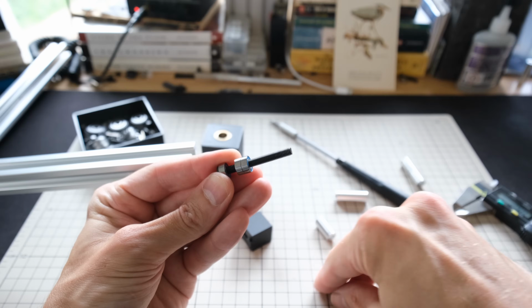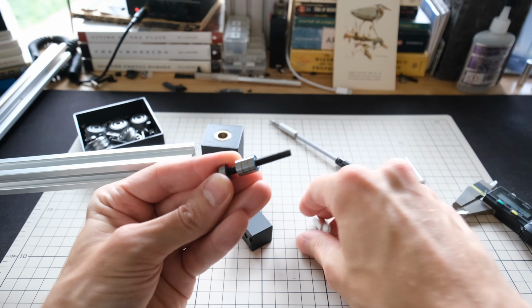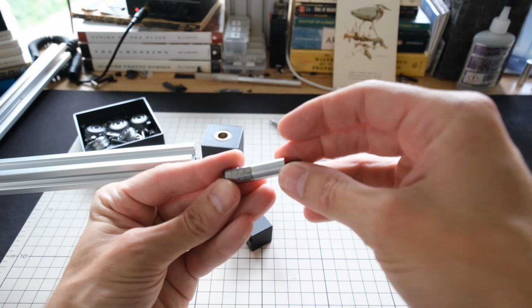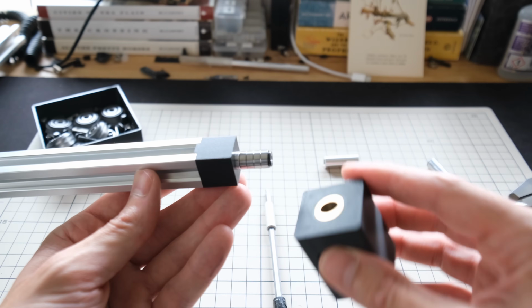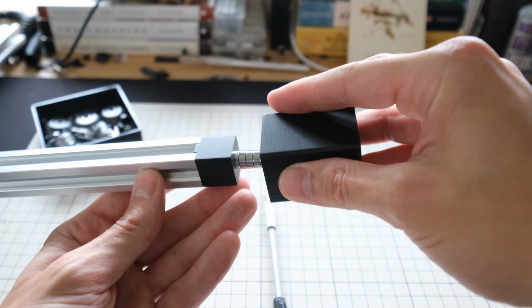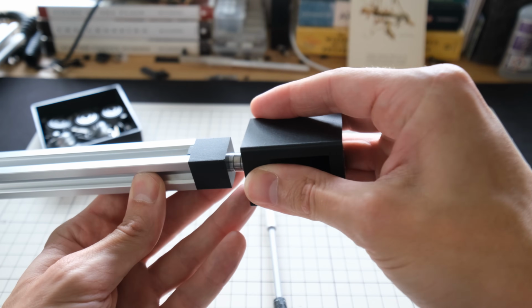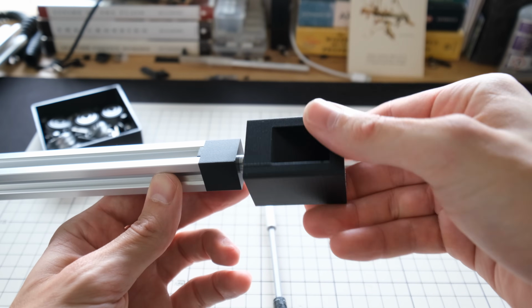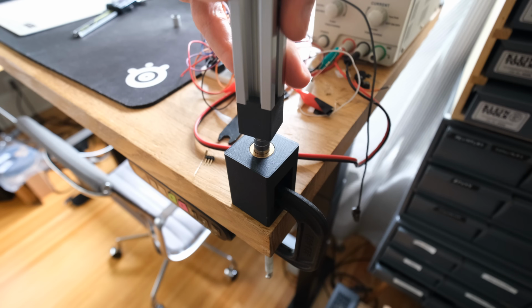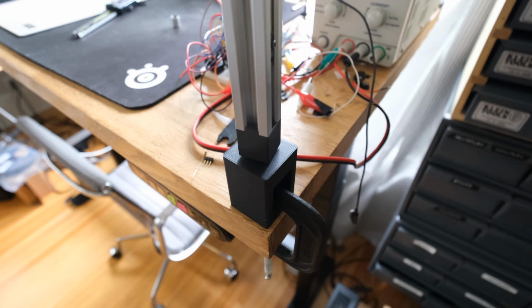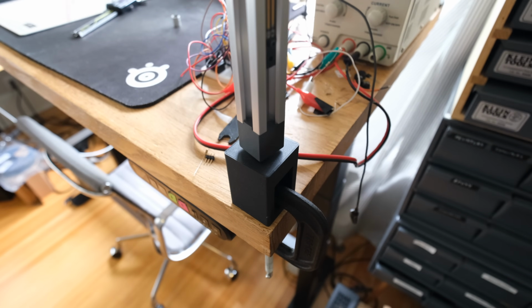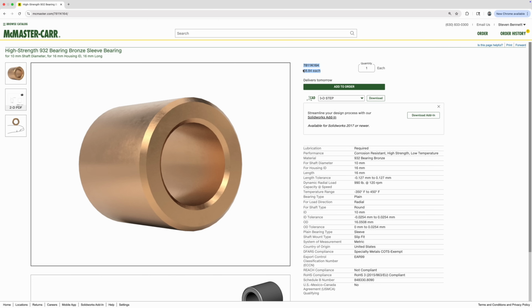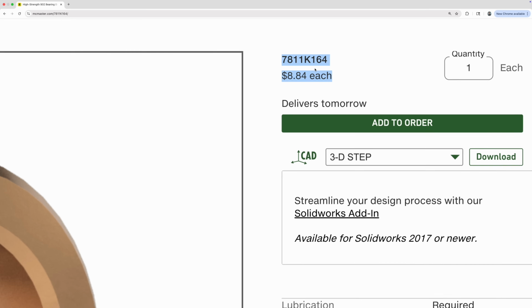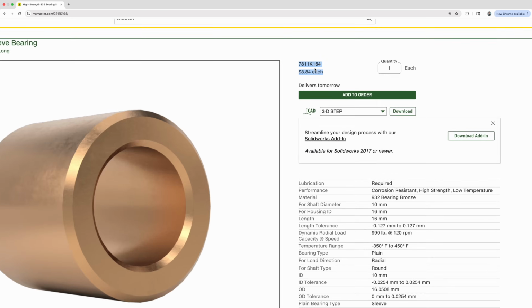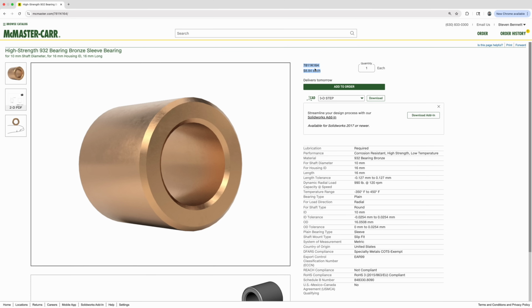And using a couple of these 10x4mm bearings, we get a consistent outer diameter with a high degree of precision while keeping costs low and sticking to off-the-shelf parts. A stack of 4 of these bearings fits perfectly into the base and reduces wobble significantly, so that's great. It's a bit awkward though because now we have ball bearings nested within a sleeve bearing and the whole thing is just a little redundant. Also, these bronze sleeve bearings are $8 each, so as much as it hurts me to see one of my favorite parts of the lamp go away, I can't help but wonder if there's a good solution out there that doesn't use the sleeve bearing at all.